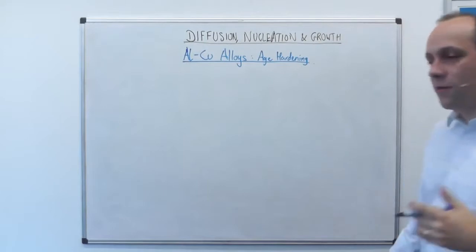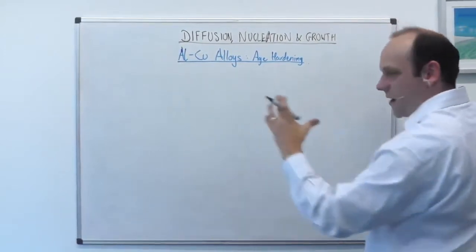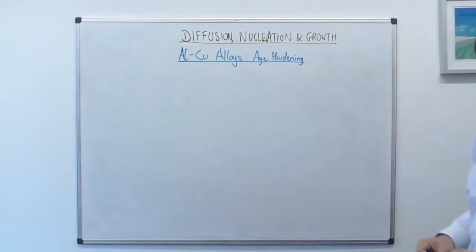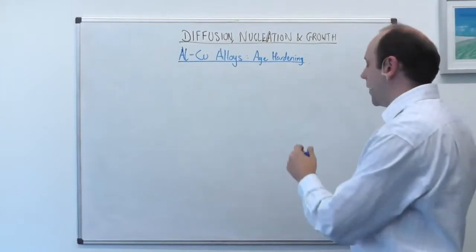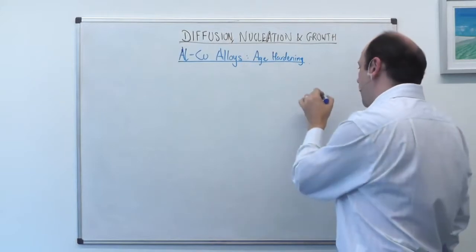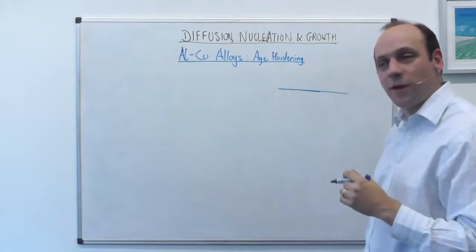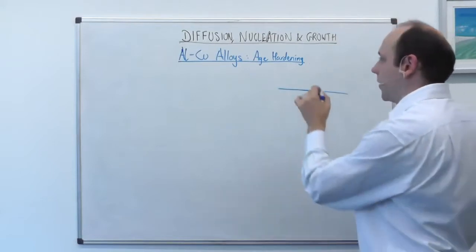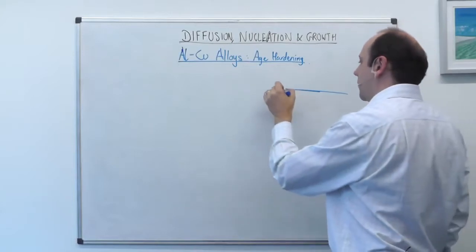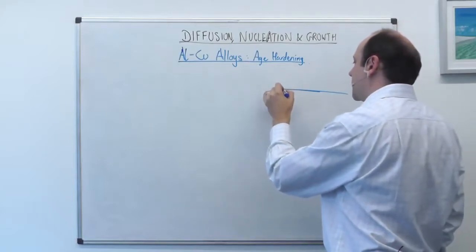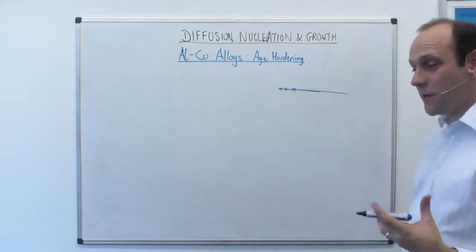And what you find is that the first precipitates you form, so you're in a big copper enriched aluminium grain, then say you're in that grain, then what you form first is a tiny little disc, 1 or 2 atomic layers thick, of alternating areas of aluminium and copper, which is called a GP zone.